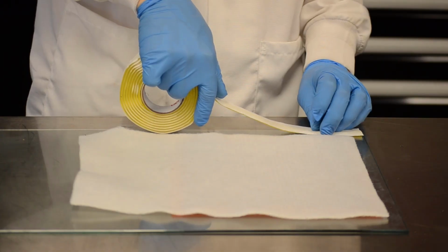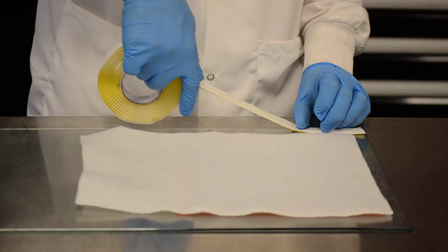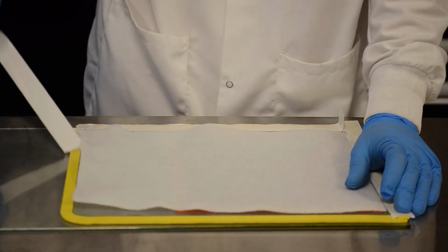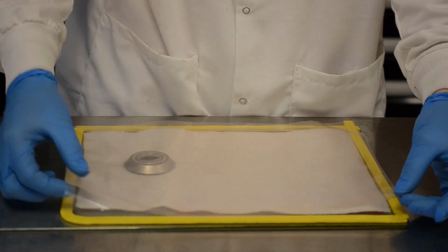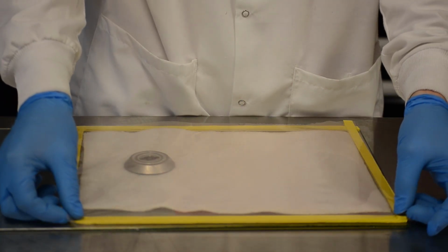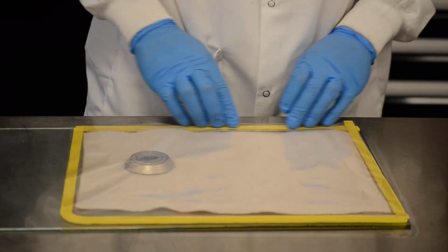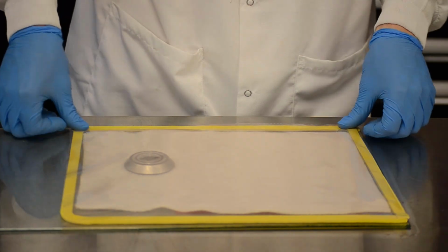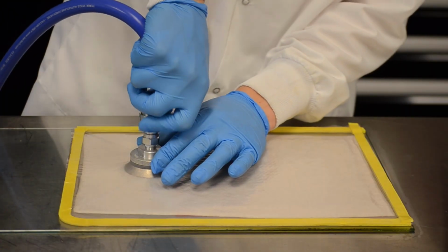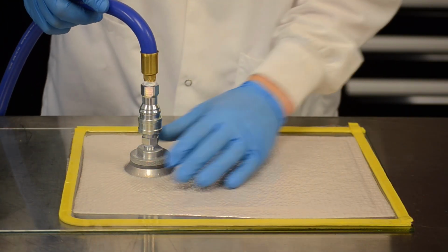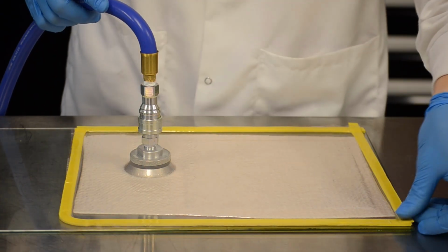Debulking consists of placing a vacuum bag and pulling vacuum on the layup to remove air from between layers and to compress the plies against the tool closer to their final position. Debulking can reduce part defects such as bridging, wrinkling, porosity, and waviness. Parts with complex geometry may benefit from more frequent debulking than flat ones.